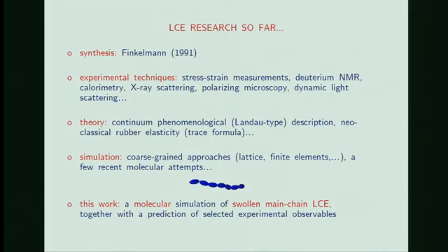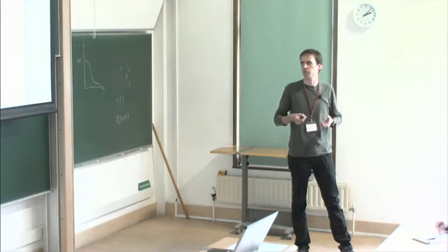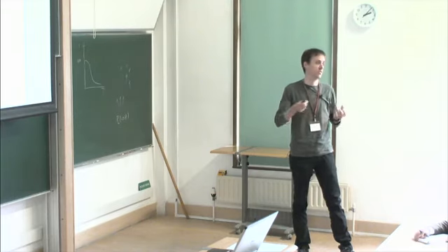If you don't take care when you synthesize your system, when you polymerize and cross-link, you will end up with a so-called polydomain material, where the orientation of the nematic director changes from domain to domain. The same is true for the local elongation. If you want to use such a material for some actuation purpose, all the domains should act coherently, and the best way to achieve this is to have just one domain.